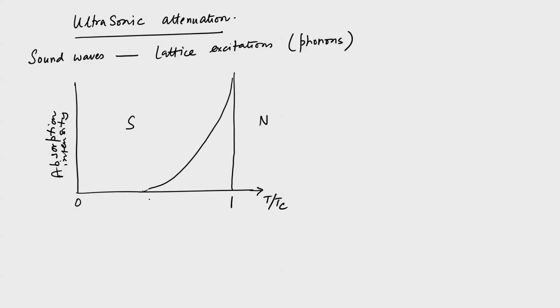Say there are a few unpaired electrons, those will absorb the sound. As you go deeper into the superconducting regime by reducing the temperature, the number of such unpaired electrons goes down drastically, and so the ultrasound attenuation also goes down drastically, going to 0. So the absorption intensity will go to 0, which means that if sound waves are sent through a superconducting specimen, they will propagate without any significant absorption. One would get the same intensity of sound as the incident sound.